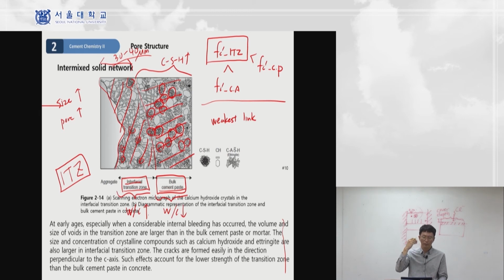Okay, so that means it has higher volume of water, so there's more space, more pore, because pore now is the volume of empty region, and pore filled with water. Both are considered as a pore. So there's more space. Subsequently, they have more porosity, and there's less cement because water to cement ratio is high. So there's more water, and there's less cement. As a result, there's less calcium silicate hydrate formation. You will learn later about this mechanism in great detail.